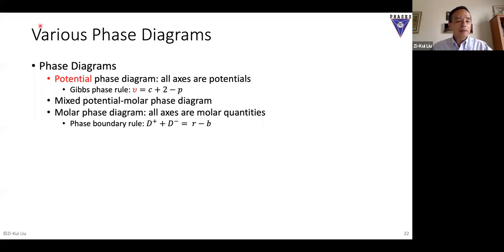For the PT diagram, you can use the Gibbs phase rule. Then you can change one of the potentials to a molar quantity, like you can change the pressure to volume, then you get the mixed phase diagram. And if you change all the potentials to molar quantities, then you get the molar phase diagram. For the molar phase diagram, you can use the phase boundary rule. But it's important that the Gibbs phase rule cannot be applied to these two diagrams, because the Gibbs phase rule is for potentials only.